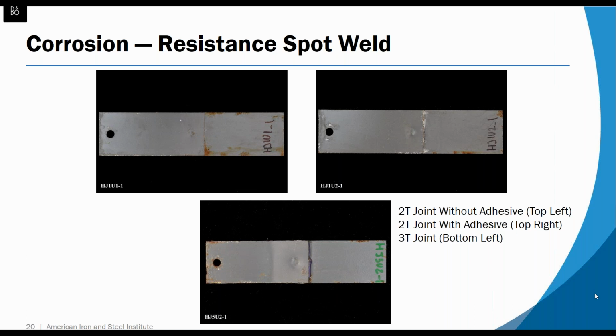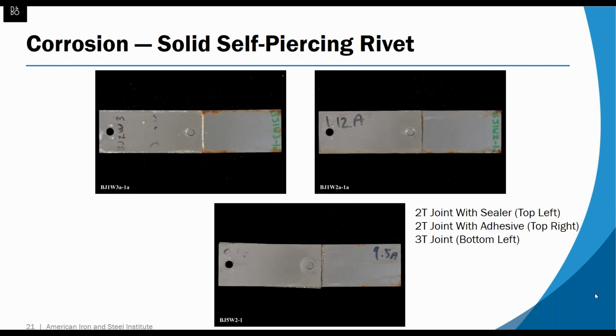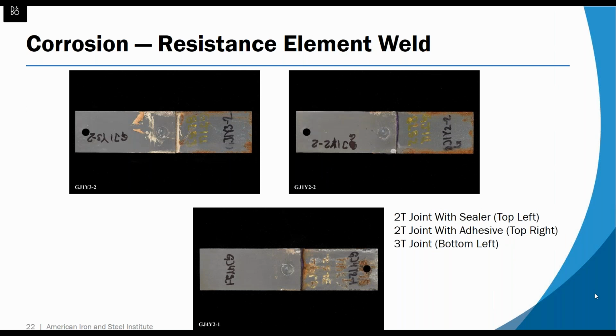These are the resistance spot weld baselines, and as one would expect, there's no significant corrosion issue with it. This is the solid self-piercing rivet, so there's a little bit of cosmetic corrosion, a little white corrosion around the insert, but nothing significant structurally. These are resistance element welds.